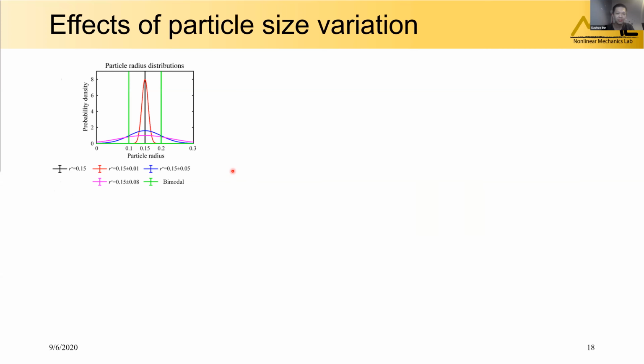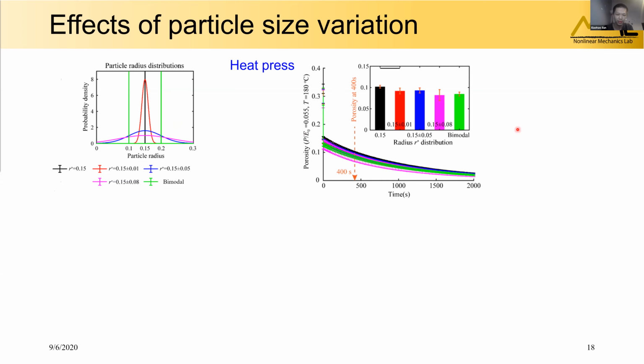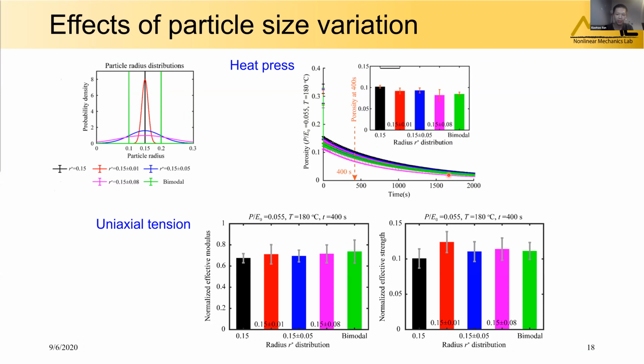So now we study the particle size variation effect. We consider non-uniform particle size in 5 different cases with the same average size. The first 4 size groups follow the normal distribution with different standard deviations. The 5th group uses 2 distinct particle sizes. On the right-hand side, we show the porosity evolution for the 5 cases. And we see that the particles with the mixed size show lower porosity than the equally sized particles, implying better consolidation. And also from the comparison of mechanical properties, we again see the particles with mixed size can achieve a higher strength after the fusion.